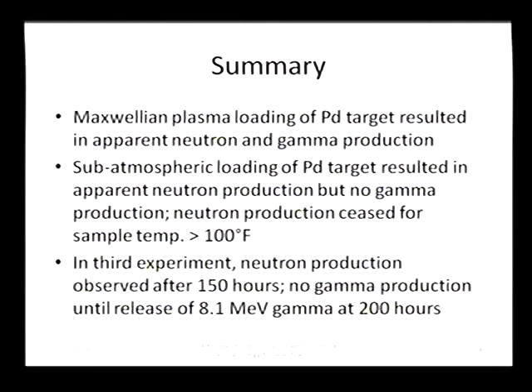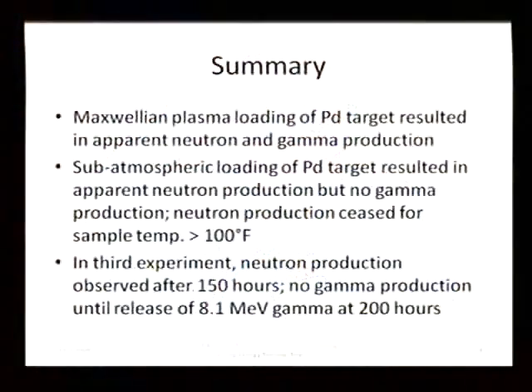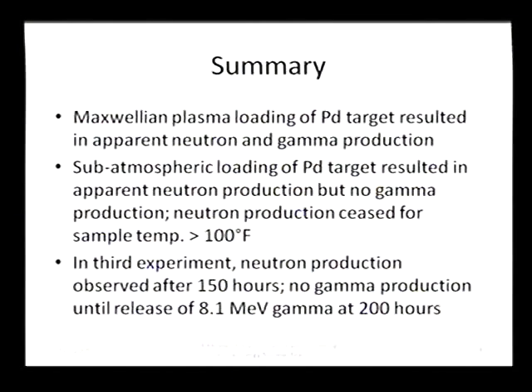So basically, that particular event, that release of 8.1 MeV gammas at 200 hours, was somewhat unusual. And we have talked with George Miley and Heinz Hoare about it, and they have scratched their heads, and they think basically that they have a theory for it, which involves clustering. And that may or may not pan out, but in this business, that's pretty standard. You have a theory, you hope it tests data correctly, and then if it does and it meets all the other observations, then you can formulate new tests of the theory.